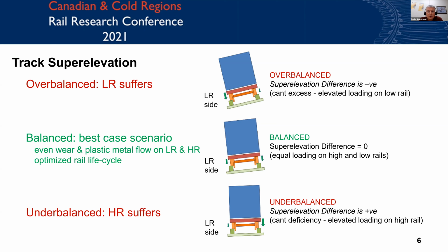In that case, you're supposed to put the even load on both rails. You're wearing them evenly. There's a propensity to develop even RCF on both rails, and it's essentially the best case scenario in terms of keeping the rail, both high and low, in track for the longest period of time. The problem is this condition only occurs for a very narrow sliver of ranges of operating conditions in track. So think of it like a scale that tips left and right, and this is the center of that scale. You have to be perfectly in line with all the conditions being lined up to keep that balance in check.